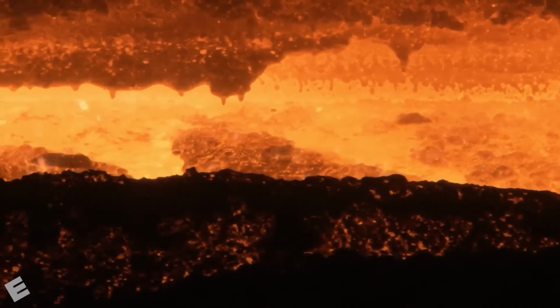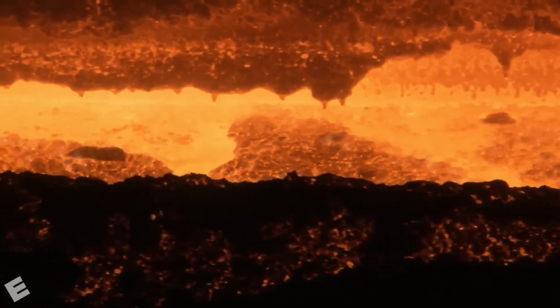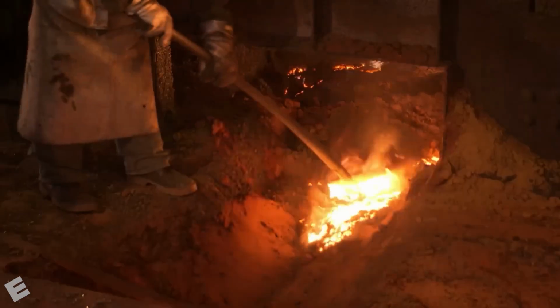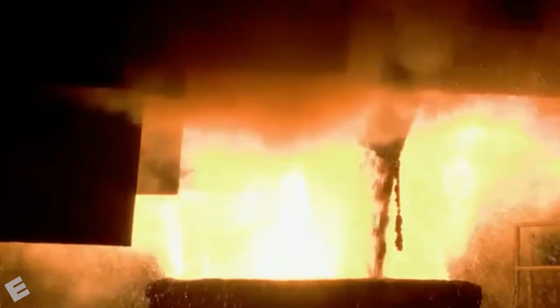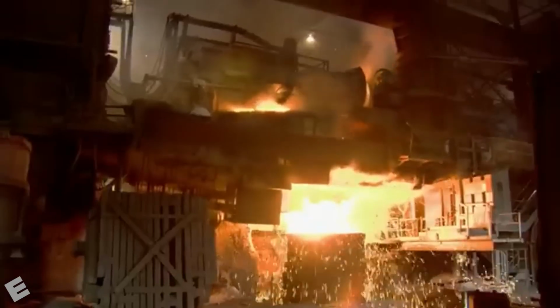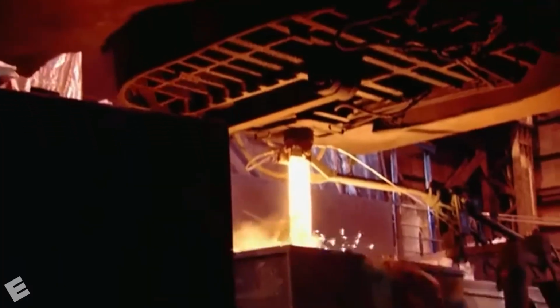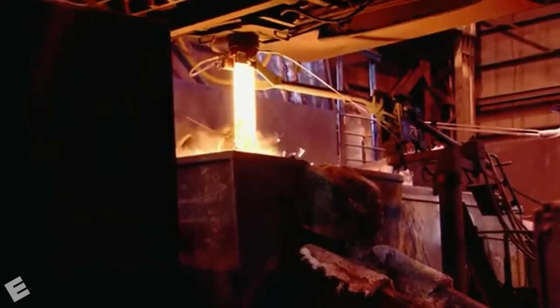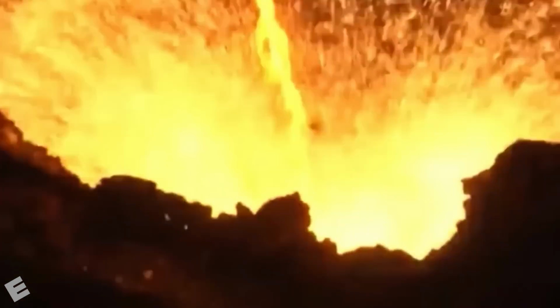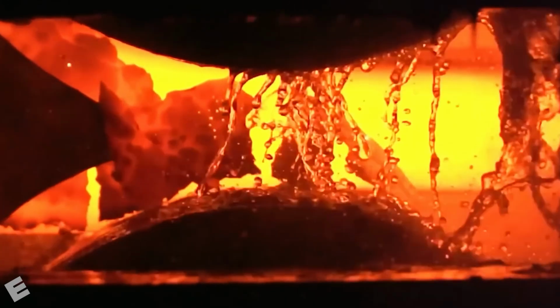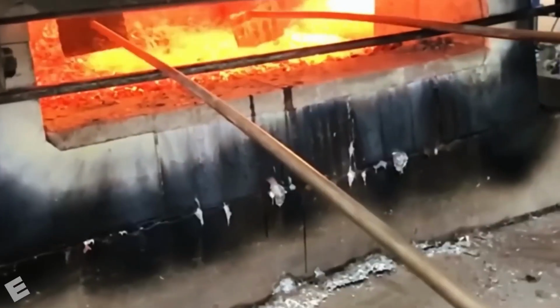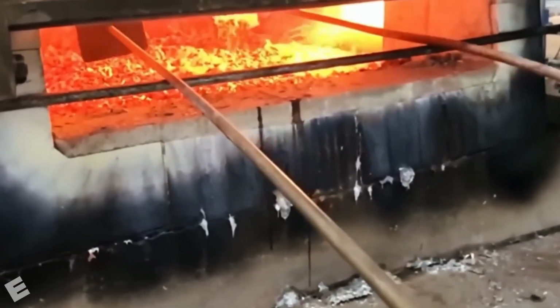The molten iron is then refined into steel. Oxygen removes excess carbon and unwanted elements, while carefully measured quantities of carbon, manganese, silicon, and other alloying elements are added to create the exact steel grade required for the rail. The chemistry is tightly controlled. Rail steel must resist wear while remaining tough enough to bend and absorb impacts without cracking.